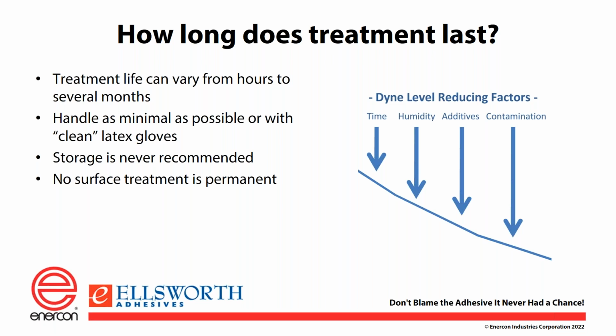So you want to do that as quickly as possible, but technically you can have 2 to 3 to 4 days before the treatment goes down. We do measure that, and we can send you samples at different levels, and then you can test those levels and say, okay, we need above 59 or 69 or 49 or whatever it is in order to make the part that we're looking to make, and then we can work with you on how to do that repeatedly.